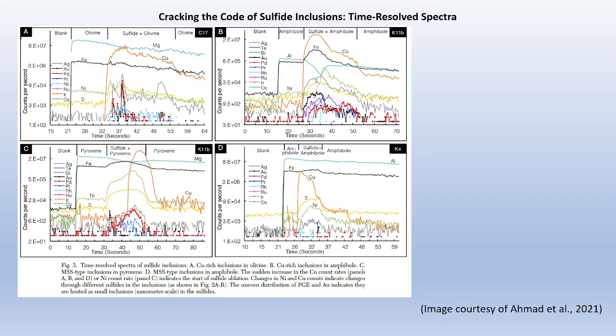In panel C, the spectrum comes from a monosulfide solid solution, or MSS-type, inclusion in pyroxene. And what stands out in this panel is a dual spike in nickel and copper, suggesting that the sulfide itself is zoned and likely recording a transition between MSS and ISS domains. This is the kind of fine-scale partitioning you would only catch with laser ablation data, and it's rare to see it preserved so clearly in a natural system.